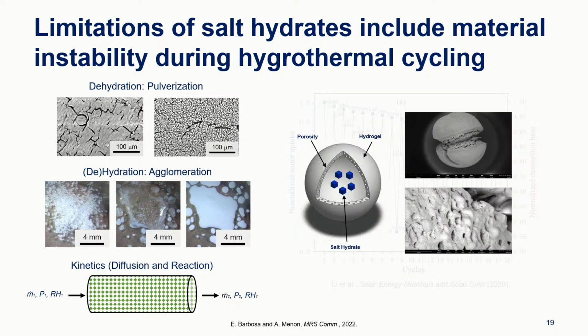So one of the things we're looking at is trying to stabilize the salt hydrates. And so we're making an inorganic-organic composite. So here's the salt, the inorganic material, and then we encapsulate the salt within a hydrogel network, which is still highly porous. These are SEM images of some of the initial syntheses we've done. So this is now the encapsulated salt, and the structure is still porous to allow you to do your heat and mass transport, but the salt is held in place so that it cannot just leak out or pulverize. So we've seen some improved performance in terms of cycling using these matrices.